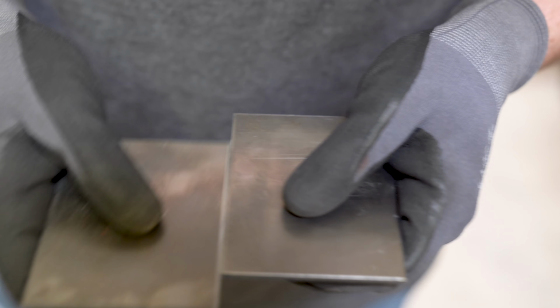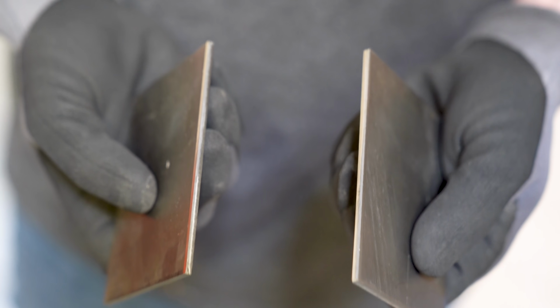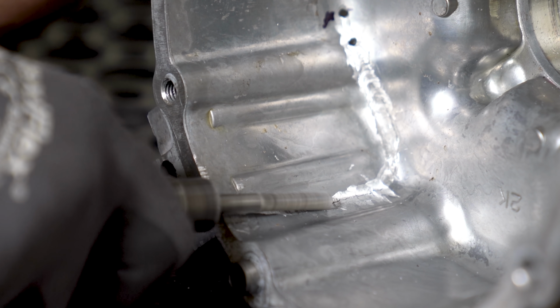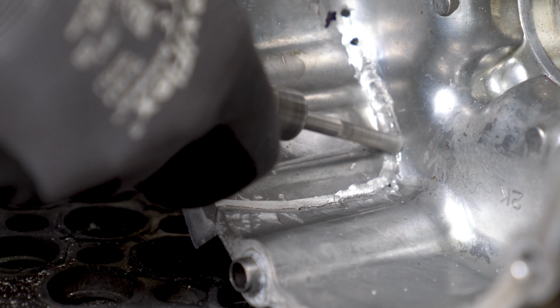There is a small fracture area, but it's virtually impossible to stick the two of them back together in a repeatable position. When a part cracks, it almost never comes out completely straight or with a perfect smooth cut line. Instead, it fractures, leaving several surfaces which form a mechanical lock when pushed back together. Think of it as kind of a natural position memory, if you will. So if we take all of the surfaces away with the groove, the mechanical lock will be removed and the part may not align properly when the repair is completed.